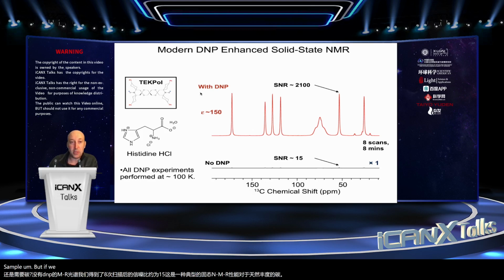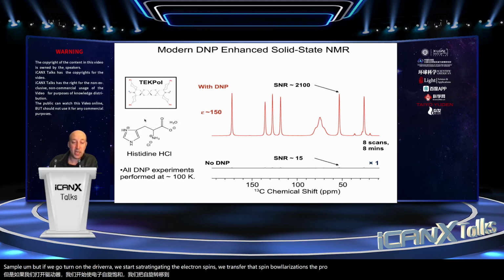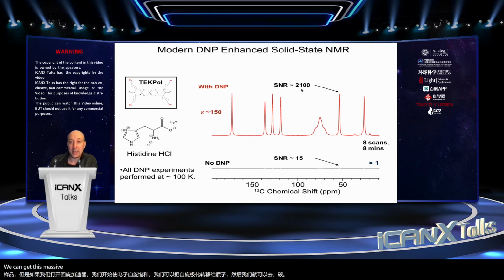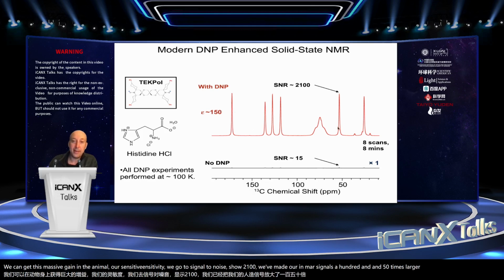But if we turn on the gyrotron, we start saturating the electron spins, we transfer that spin polarization to the protons, and then we go to the carbon, we can get this massive gain in the NMR sensitivity. We go up to a signal-to-noise ratio of 2,100. We've made our NMR signals 150 times larger and brought them above the thermal noise level.